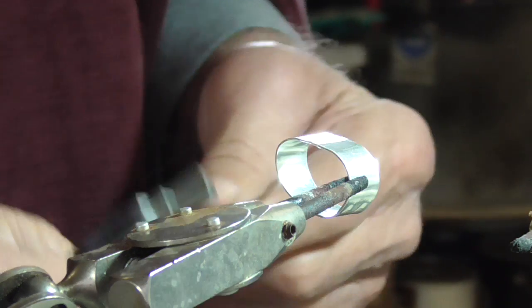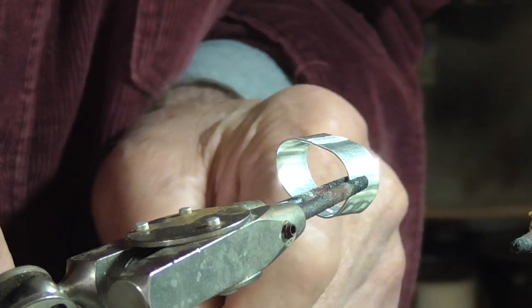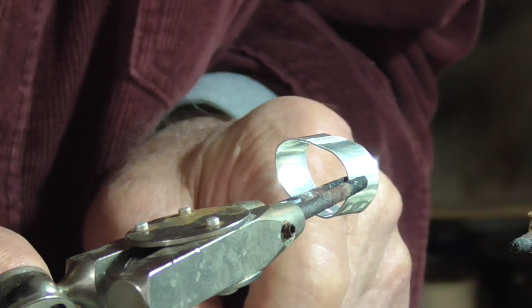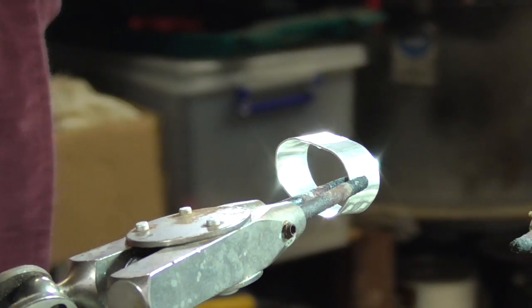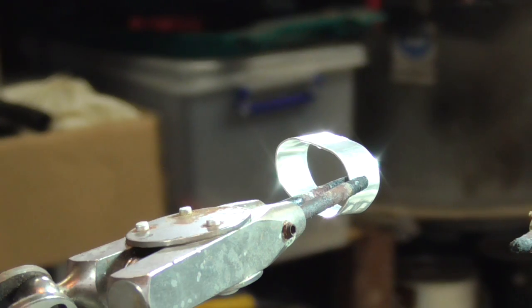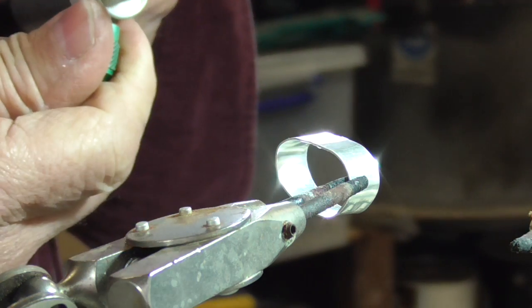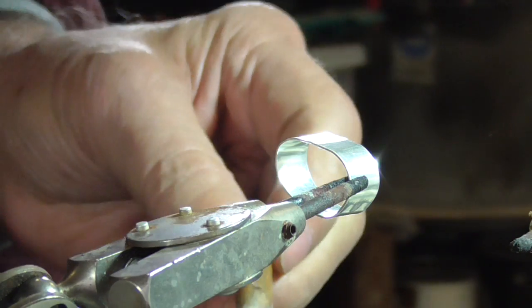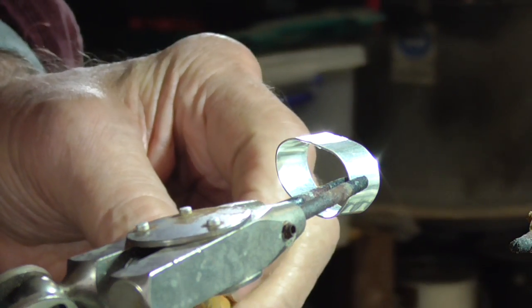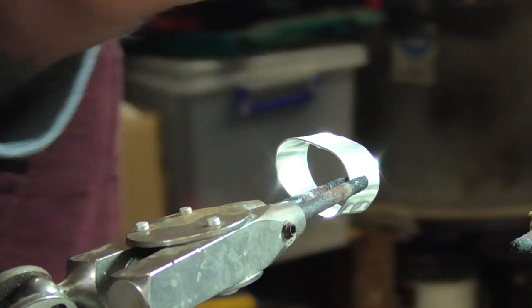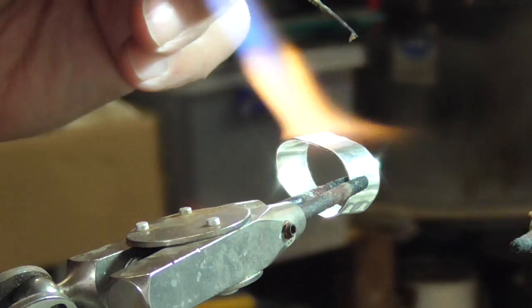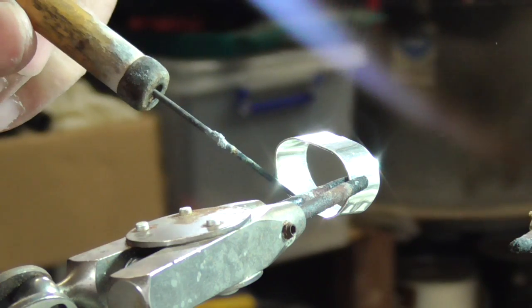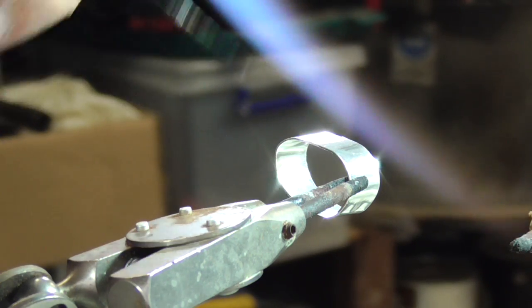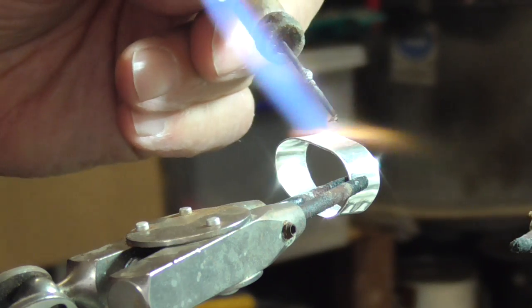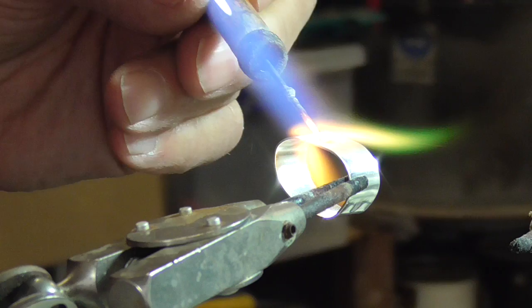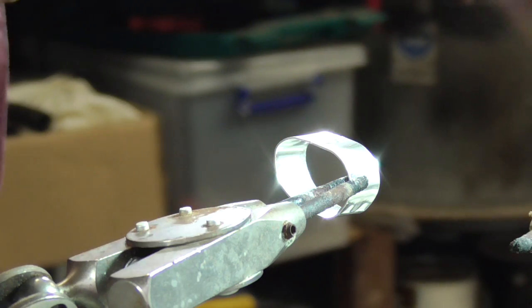And we're going to use hard solder for this. 2 small pieces. And I'm going to pick those up on my solder pick. Tungsten solder pick, and you can just heat it up. Touch the solder, it'll jump onto the pick. Now this one I'm heating from the top. I don't want to heat the lower part of the ring, otherwise it'll expand and open the gap up. I'm just heating the top, place the solder flows, and that's it.